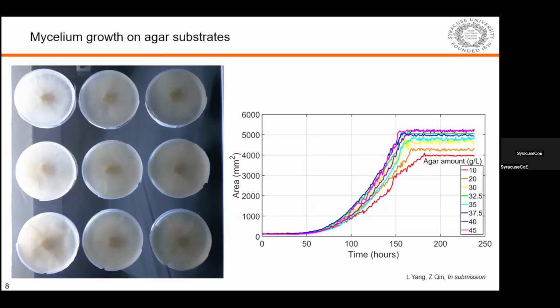That's something very interesting, because here we intentionally kept the nutrient amount the same, and we just changed the agar amount. So that suggests that the mycelium, while it's growing, can also sense the stiffness of the substrate. We have a paper in submission related to this topic.